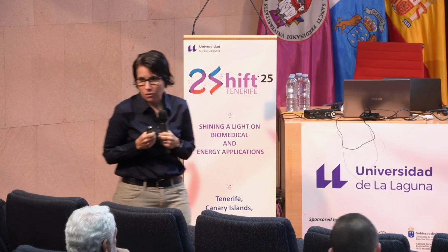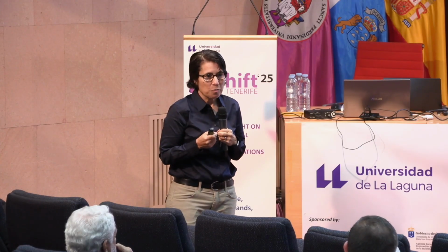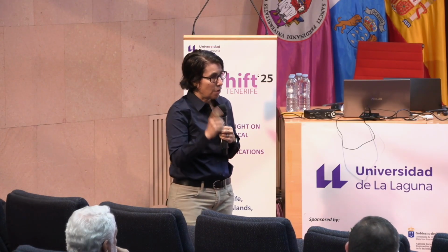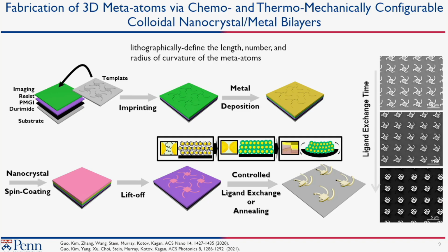But what we wanted to do is tackle this challenge of, could we make structures in 3 dimensions and only use 1 lithography step and do it over large areas? So we make a template to use imprint lithography, and it looks like a pinwheel. The pinwheel could be all in one direction or the other to make enantiomers. We imprint into resist.